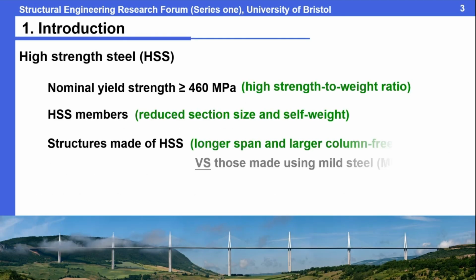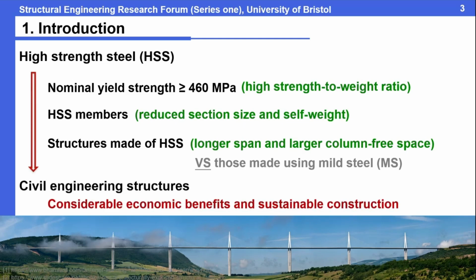So first is the high-strength steel. This kind of steel material has a nominal yield strength larger than 460 megapascal. This material has a high strength to weight ratio. If using this kind of material to make members, those members usually will have reduced section size, and the self-weight usually will be relatively lower compared with mild steel. If we further use these members to make structures, you can achieve longer span and larger column-free space compared with those made of mild steel. It means if you apply high strength steel to civil engineering structures, we can achieve considerable economic benefits and sustainable construction.